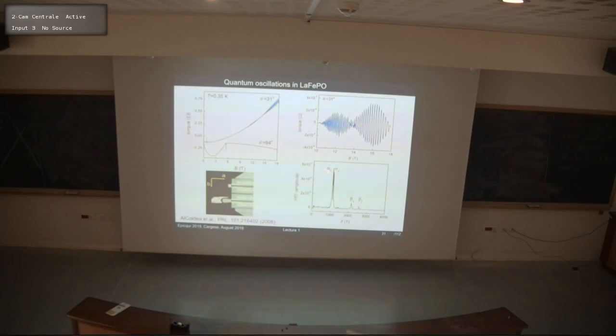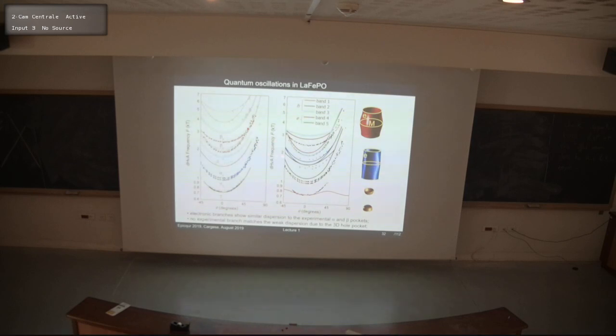Here it's quite clear that alpha 1 and alpha 2 are quite different from beta 1 and beta 2 because of their amplitudes as well. Okay? And also, actually, I don't have the graph today. I'll show you tomorrow. There is a lovely Yamaji angle right here. So this is when you have the minimum and maximum orbits, and if you rotate the magnetic field, at some point those minimum and maximum will have the same cross-section, and they will interfere constructively, and give you a very strong enhancement in amplitude at the Yamaji angle.